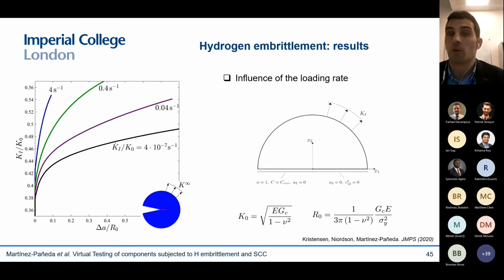Here I'm showing the influence of the loading rate, again an R curve. And you can see again what you expect to see from the experiment. If you load very slowly, then there's enough time for the hydrogen to travel to the fracture process zone, and then you see a smaller resistance of your material. So we can capture those well-known effects.